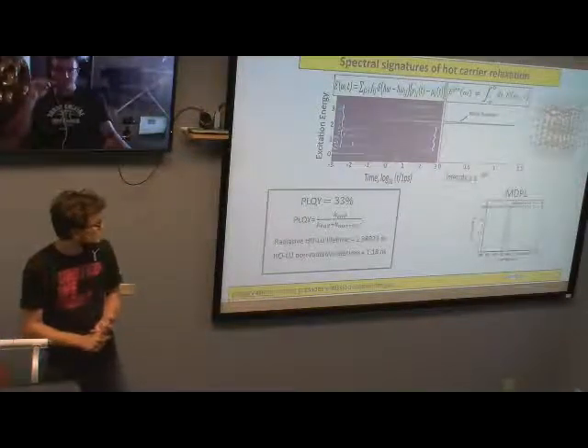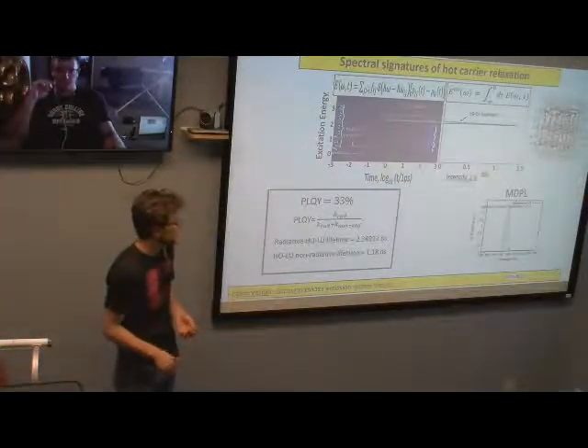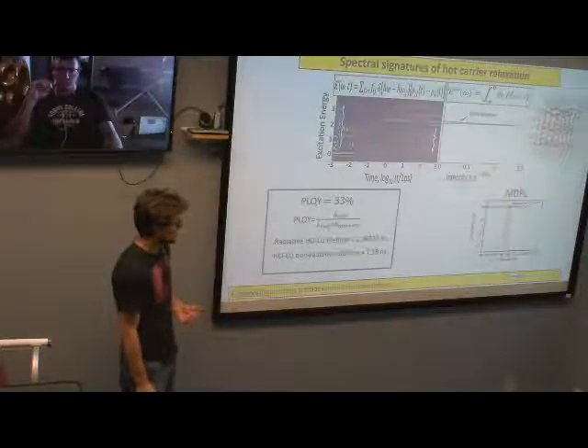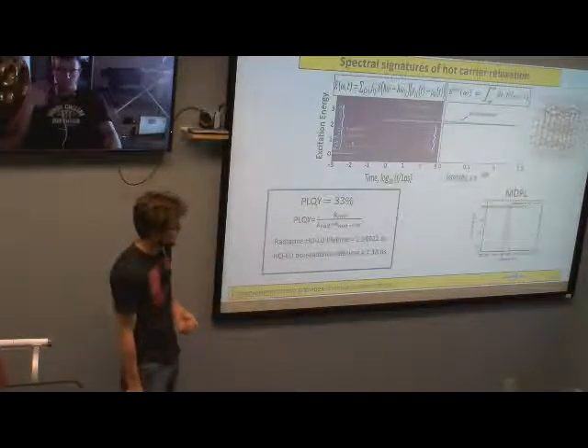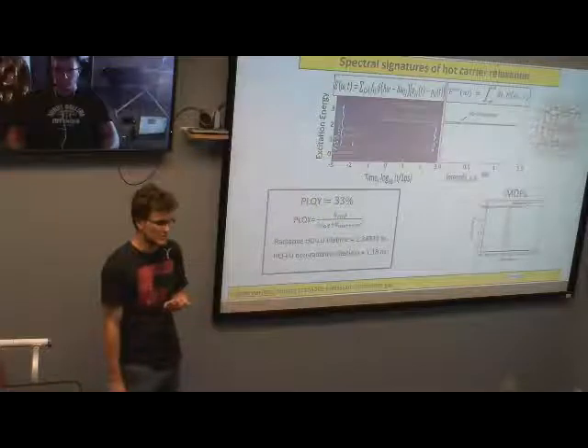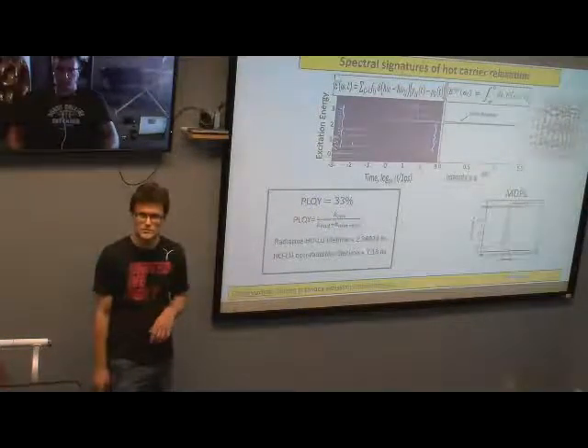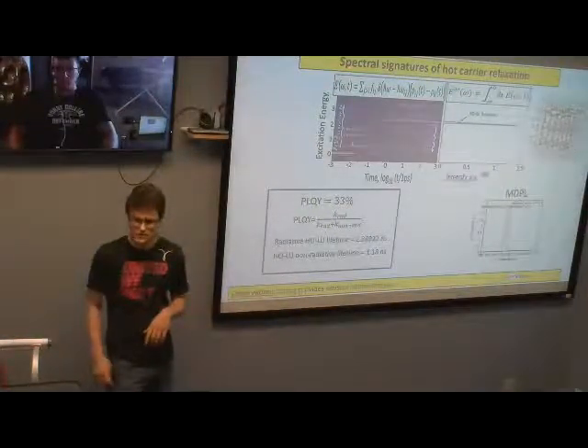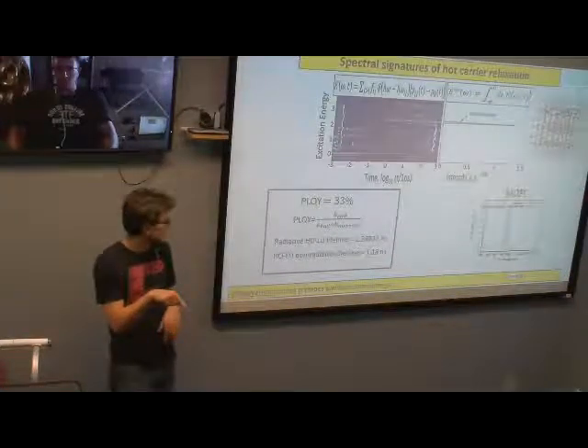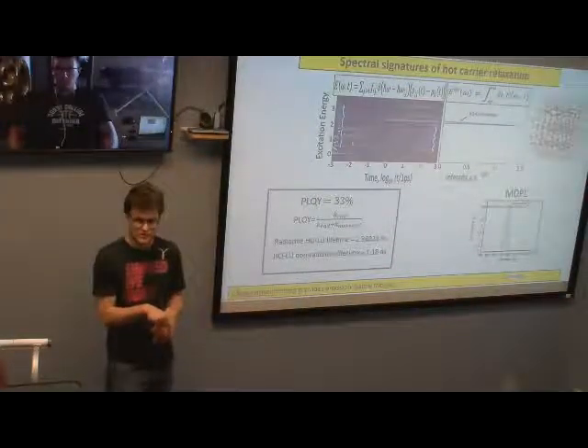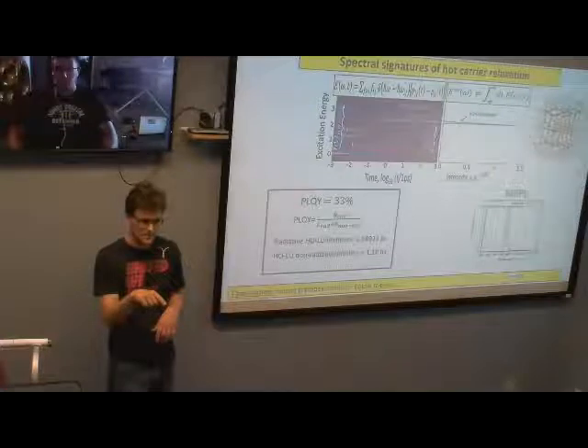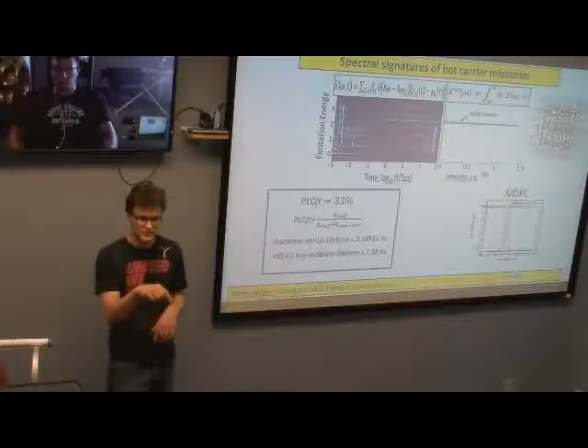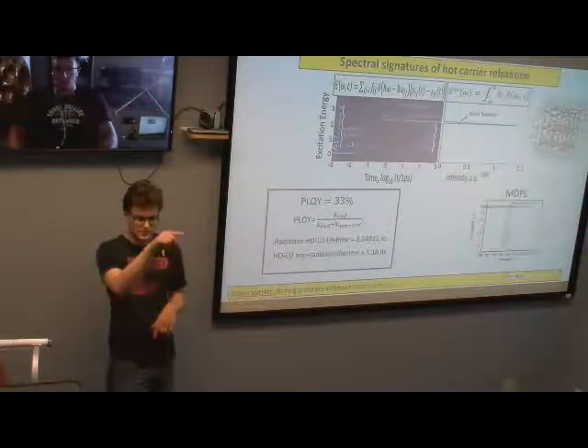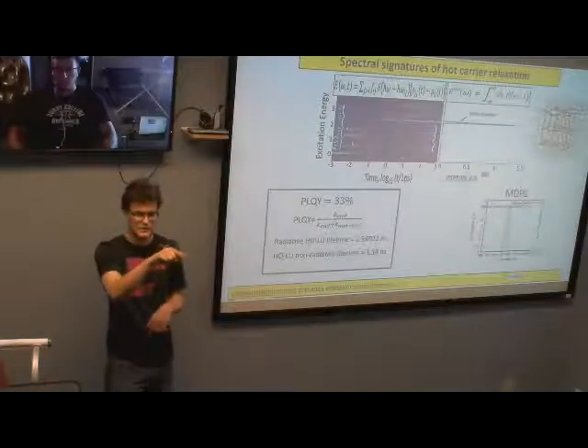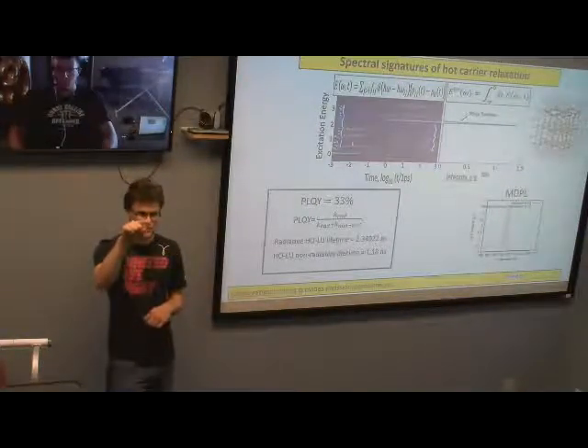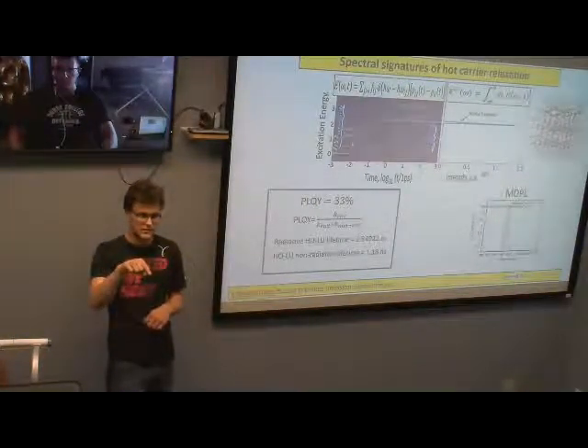And then this right figure on the bottom is just something I threw in. So this is molecular dynamics photoluminescence. Ewan's presented on it a couple of times. I think John was the first one to publish on it. So basically, from your molecular dynamics trajectory, you just compute oscillator strength in time. So if you're in your potential energy well, as you slosh back and forth, you have a probability of emitting at a certain time.